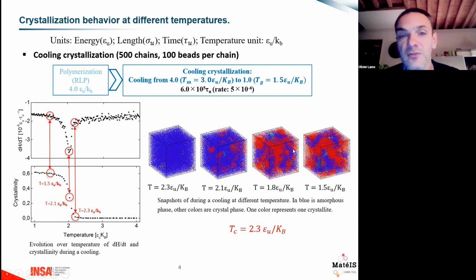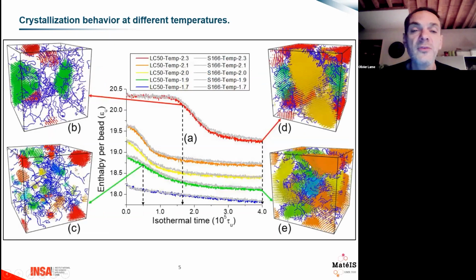At the end, we get on this system, which is a very simple system of only 500 chains with 100 beads per chain, a typical crystallinity of 60%, which is very consistent with what we can see in reality. The only problem is that this microstructure is a bit random, and we have to improve this point. But I will discuss that just after.